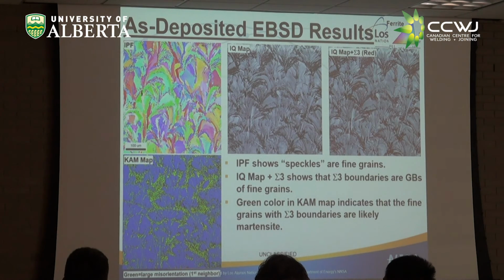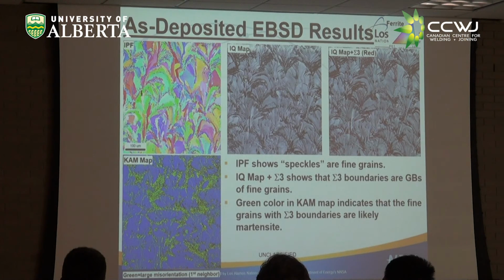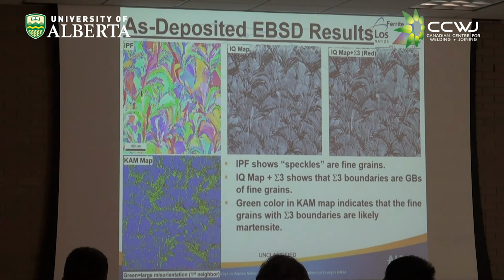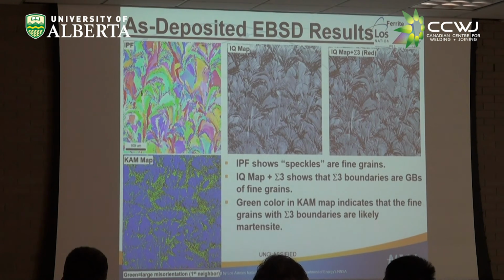So you saw from the nano indentation results that sample had much greater radiation hardening than the normalized and tempered, and then also the normalized and tempered wrought. So I don't believe that the dendritic or the cellular microstructure helped in any way, no.